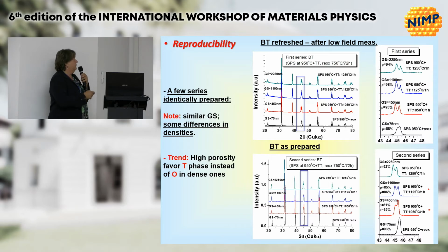Here are many samples. We checked the reproducibility of the method, and we wanted to see if this orthorhombic state is still present or stable if you repeat or if you prepare different samples. As a tendency, we found that high porosity favored the tetragonal state instead of the orthorhombic one, and this gave us the idea that stresses can be the origin.